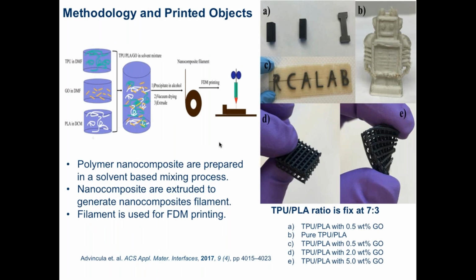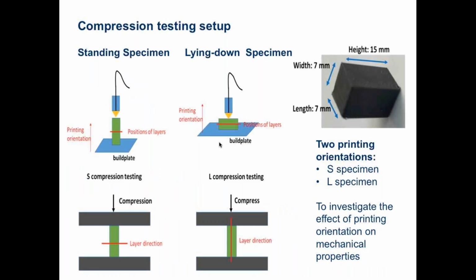So after preparing this mixture, evaporating the solvent, and then doing an extrusion to prepare the filament, we then 3D printed these devices. And as you can see here, various forms, elastomeric property is confirmed. The color is black because of the graphene oxide loading. We were able to then test the different amounts of graphene oxide and its material properties. So graphene oxide then should enhance the thermomechanical properties, and the orientation of 3D printing or 3D printability is an important parameter because 3D printing is an additive layering technique. Therefore, the direction of printing, parallel or perpendicular to the bed, makes a difference.